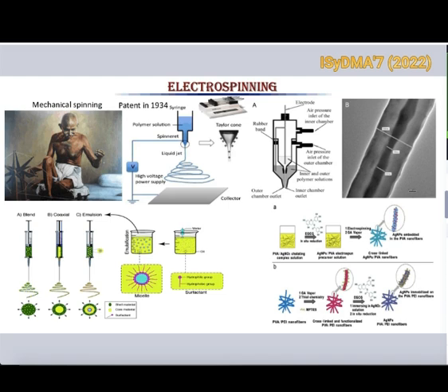As you know, electrospinning is a versatile technique most of you probably have in your laboratory. It's an inexpensive, extremely efficient, and reproducible technique that can be used to produce one-dimensional fibrous materials or composites with a wide range of diameters from nanometers to millimeters, simply by applying an electrostatic field to a polymeric solution. With the recent advances in nanotechnology, we can make different types of multifunctional materials, which are produced by combining nanomaterials and polymers in electrospun configuration.